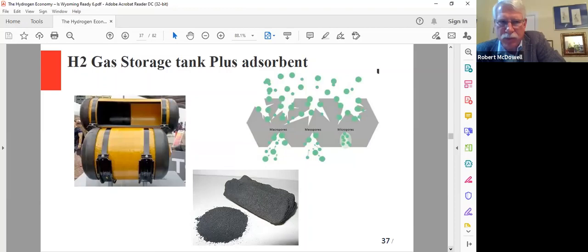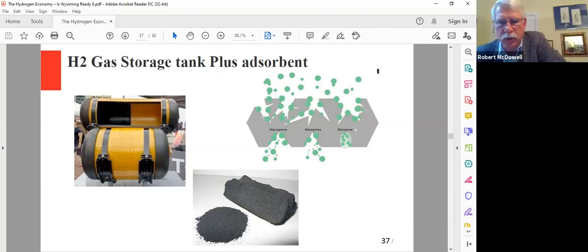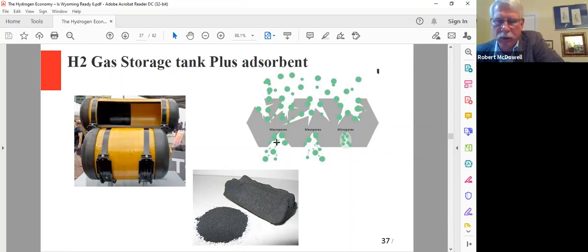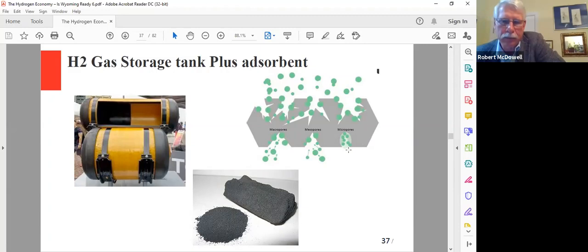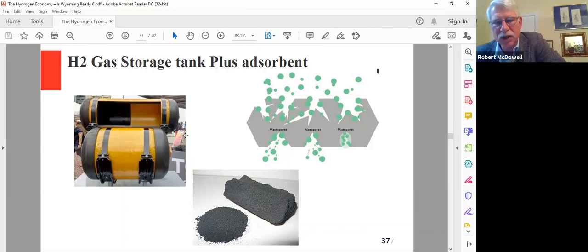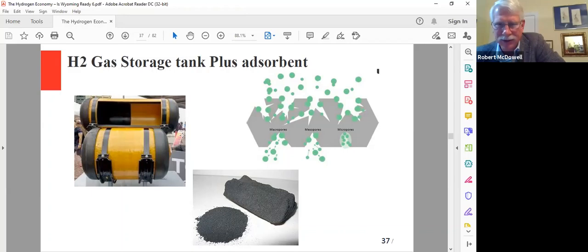If you cut that tank to see a cross-section, you can see it has a plastic liner which is impervious to hydrogen and stops any of those tiny hydrogen molecules from leaking out. Then you have the real strong carbon fiber plastic layer that gives the strength to hold the pressure. Then you have a fiberglass layer on the outside to give it impact protection. They use these fiber-reinforced tanks because the pressures are 350 or 700 bar. 700 bar is about 10,000 PSI. Very high pressure. If you tried to make a steel tank or aluminum tank, it would be super heavy. That's where the beauty of the carbon fiber material comes in.